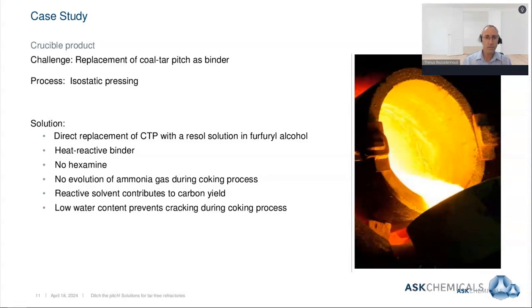Of course, being a resol, it is heat reactive by nature, and being heat reactive, we are able to eliminate the use of any hexamine. If you think carefully, in the cases where you might use a Novolac phenolic resin, you would still require the addition of hexamine as a hardener or catalyst. In our case, we chose a heat reactive resol, eliminating the use of hexamine, and through the elimination of hexamine, you also completely avoid the evolution of ammonia gas during the coking process. So another component eliminated.